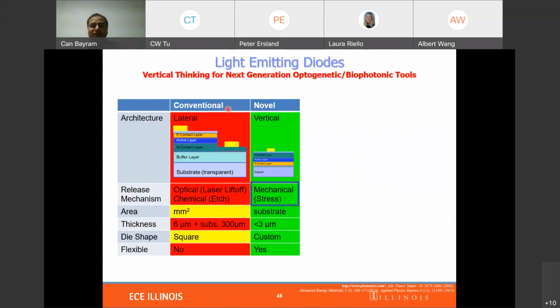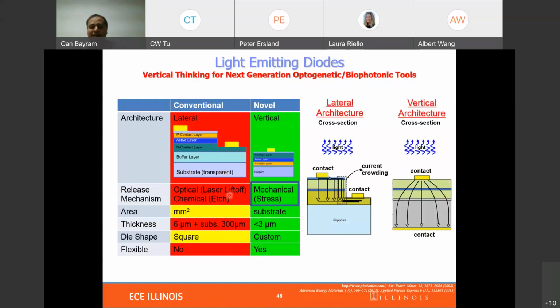Now, the conventional way of having these thin film LEDs is basically through substrate removal. Typically, you have a lateral structure, and then you have a substrate that's optically transparent, and you are using laser and chemical etch. Now, in these lateral structures, what happens is typically you always have current crowding. The current chooses the lowest resistance path, and you have more current density here, and this creates not only heating but also a reliability issue in the long run.